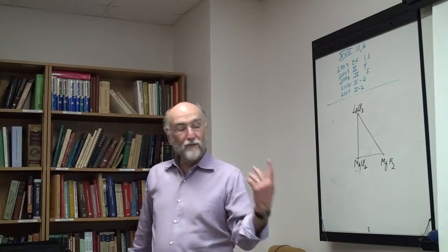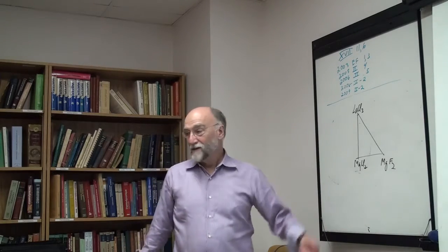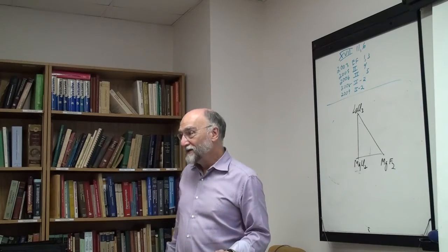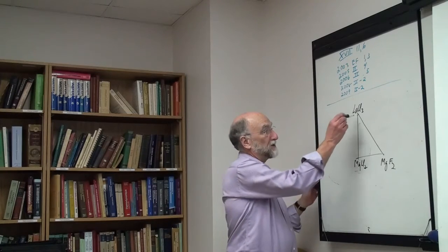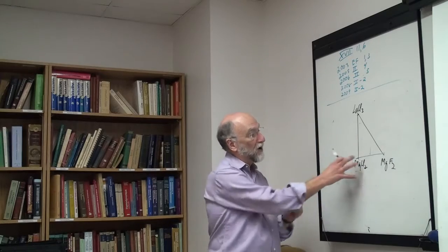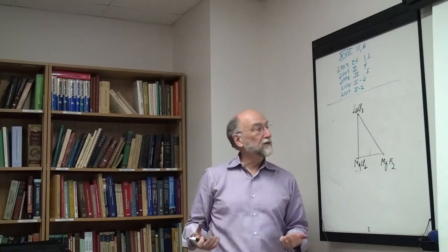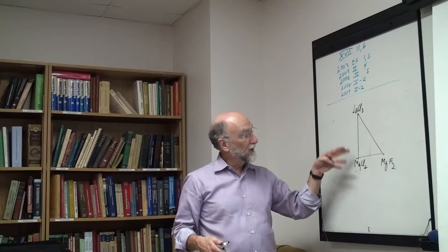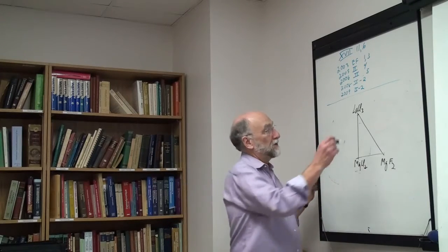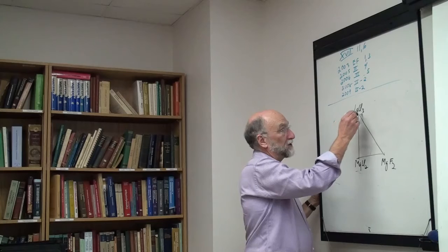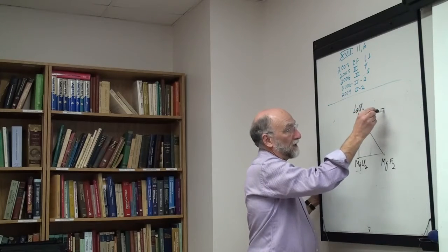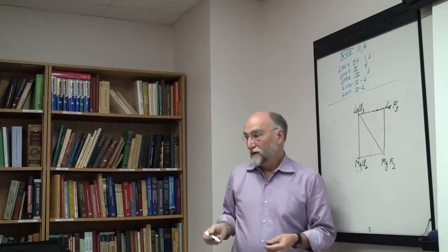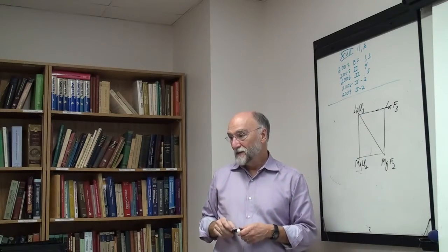Okay, so is this just a simple Kohler type thing? No, it's not, because you have 2 sublattices. This is not a system A, B, C, where these molecules are mixing on one sublattice, like 3 metals. These are molten salts, and you have a cation sublattice and an anion sublattice. You can't get around the fact this is not a simple ternary system. You've got to add on the rest of it here, and here you've got to put on lanthanum fluoride.